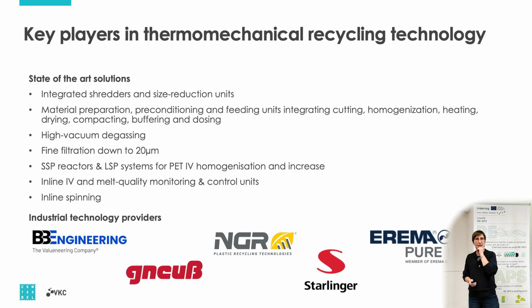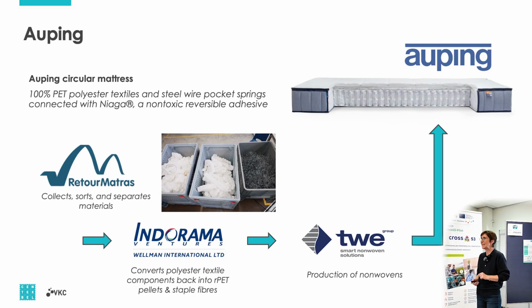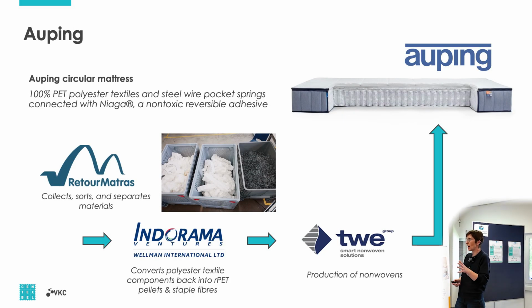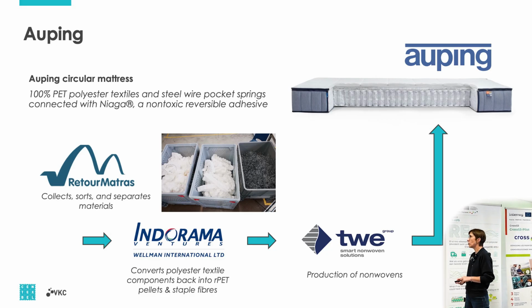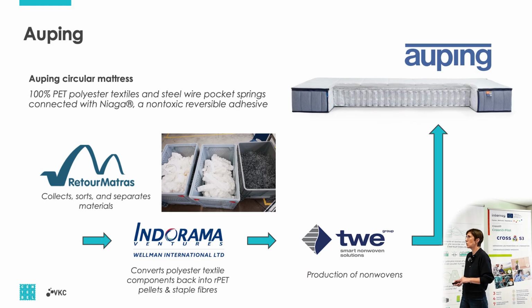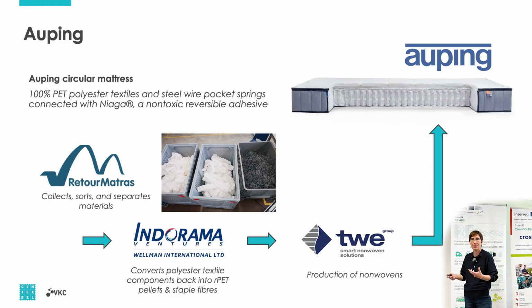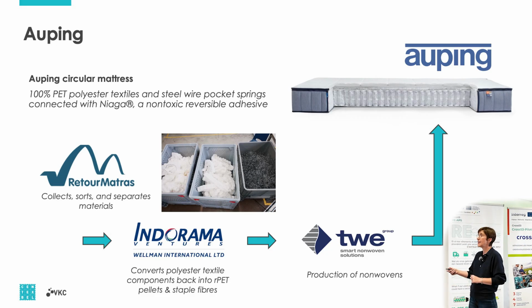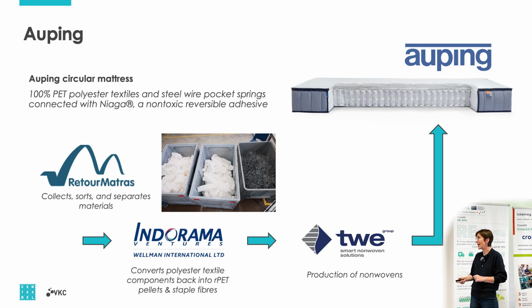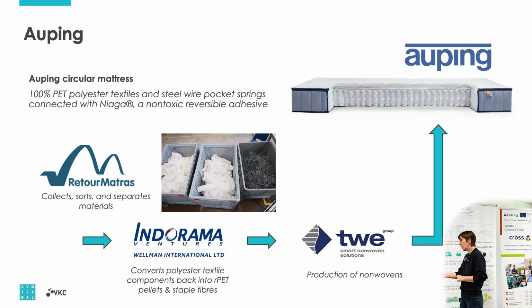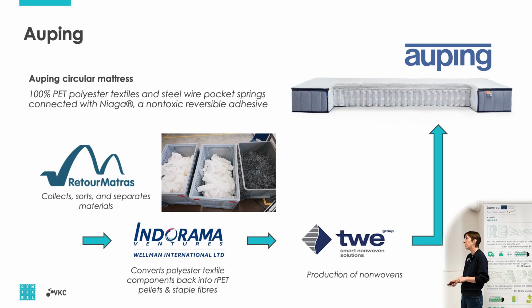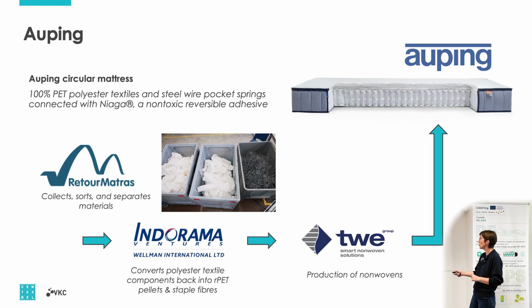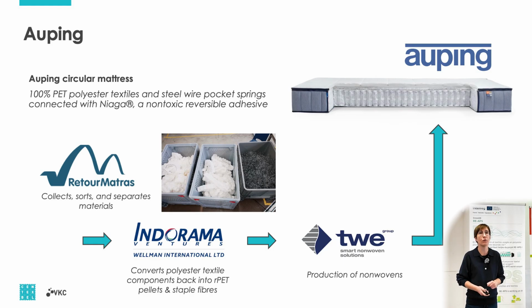As an example of what is already happening today, this is an example of 100% polyester closed loop recycling, fiber to fiber. Auping has put on the market what they call their circular mattress, working with 100% polyester structure. They are still using the steel wires, it's a pocket spring mattress, so the steel wires are removed at end of life, but all the rest is, let's say, polyester based. Also the glue that is being used to combine everything is polyester based. They take it back, so they do the collection and the sorting into all those individual fractions. Together with Indorama, they reprocess it back to staple fibers and recycled polyester. With TWE, it goes back to non-woven, and those non-wovens go back into a virgin polyester mattress.